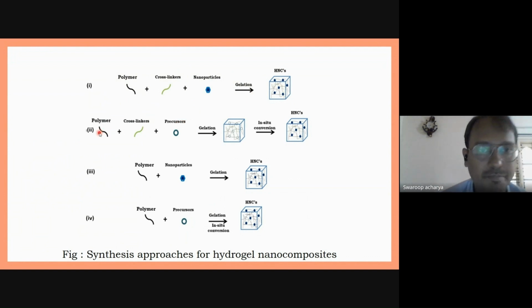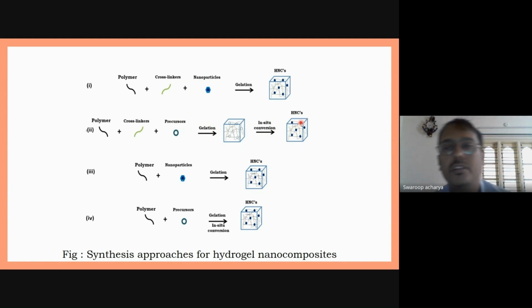In the second method, a polymer with a chemical cross-linker and a precursor material for the preparation of nanoparticles will be used. During the gelation, the precursor material will not be reduced to the nano size. After that, by using other chemical techniques or irradiation techniques, we can reduce these precursor materials into nanoparticles, and in the final product, the nanoparticles will be isolated within the structure of the hydrogel nanocomposites.